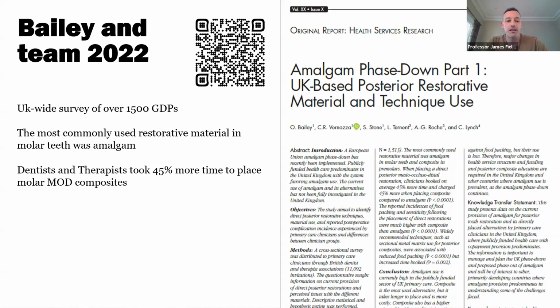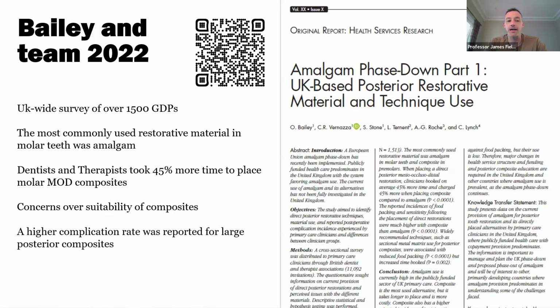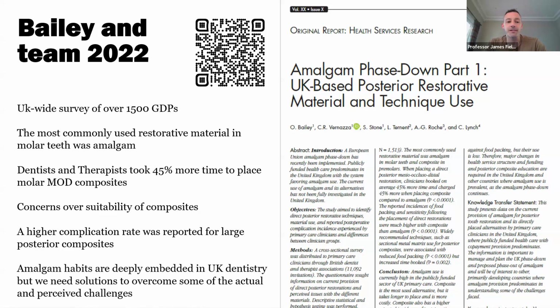Interestingly, though, the study showed that dentists and therapists took 45% more time to place molar MOD composites than they did with amalgam. And largely, people had concerns over the suitability of composites for those larger restorations. And a higher complication rate was reported for large posterior composites. And I guess what that's showing us is that amalgam habits, whether we like it or not, are deeply embedded in UK dentistry. And we need solutions to overcome some of the actual challenges, but we also need to talk about things like this tonight because we need to overcome some of the perceived challenges.